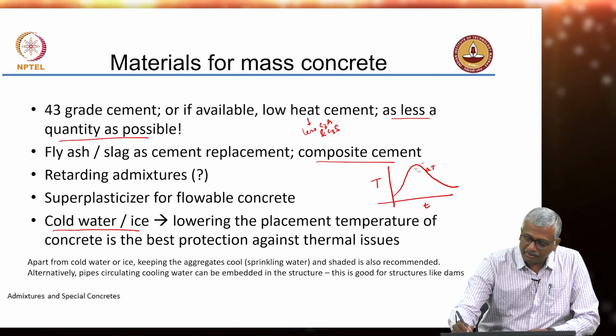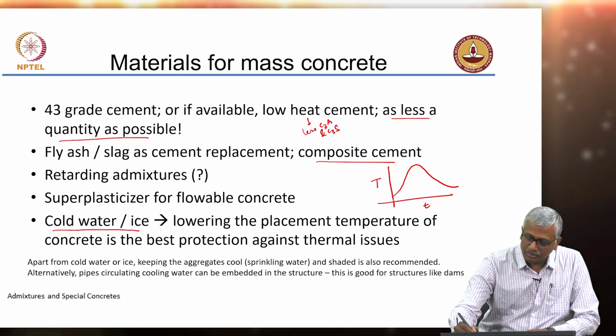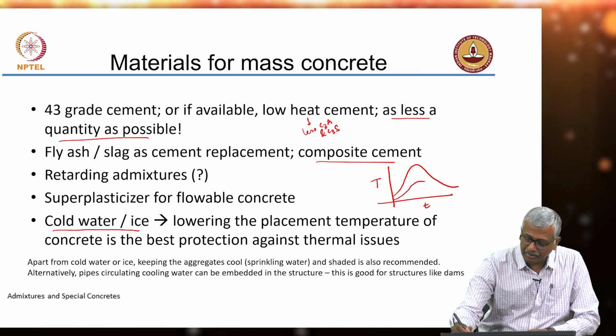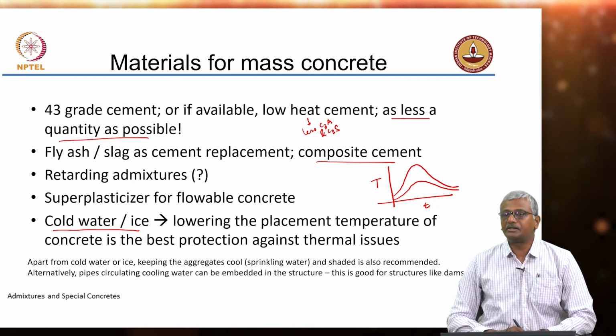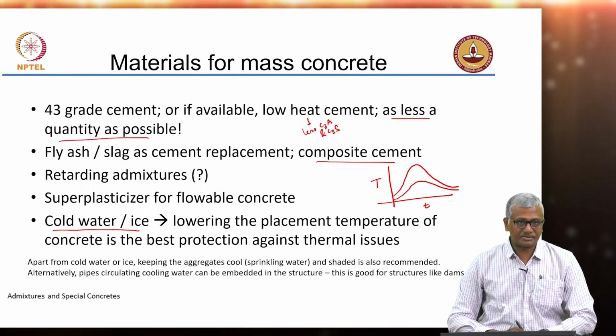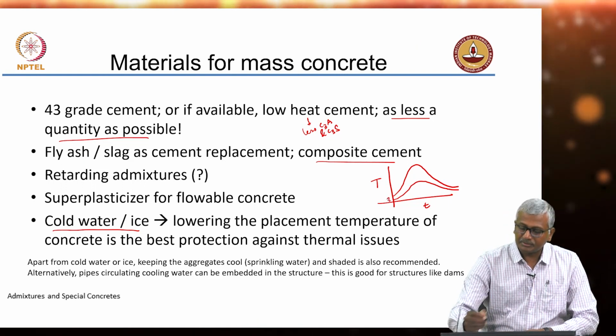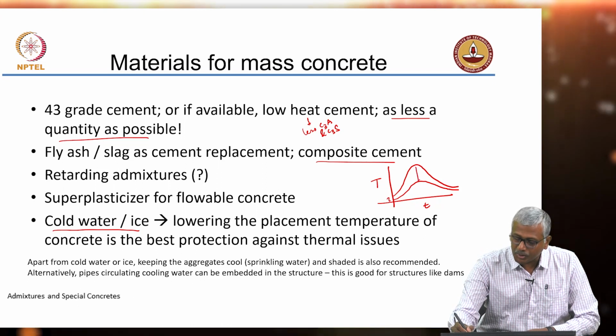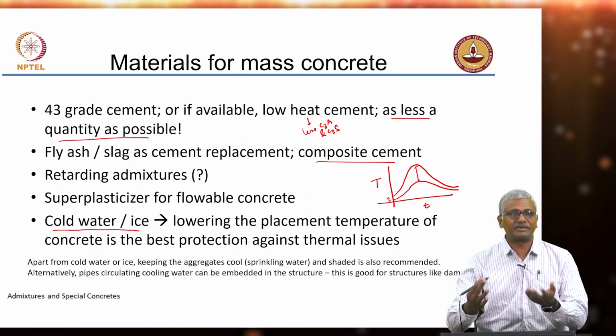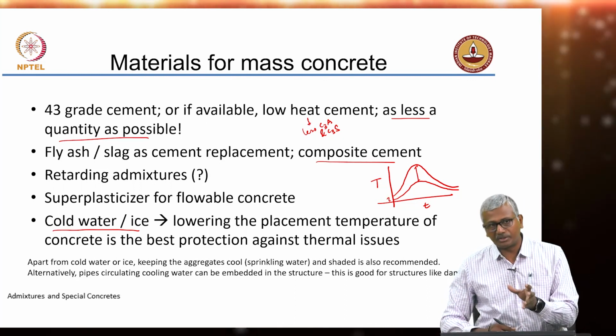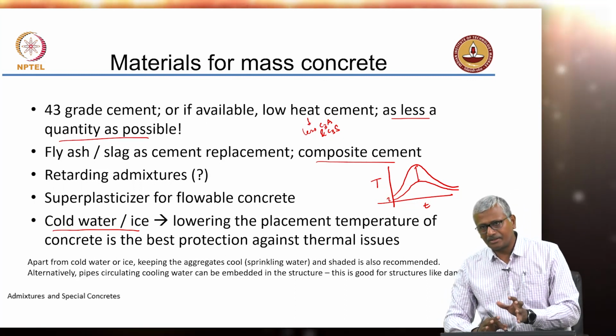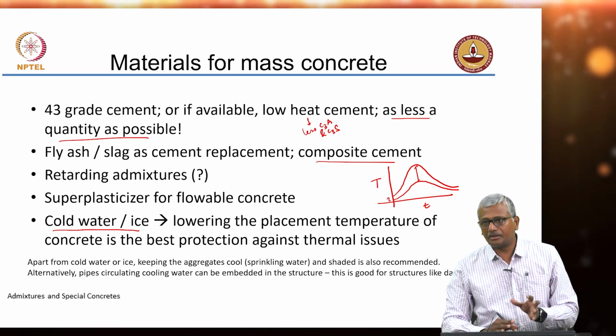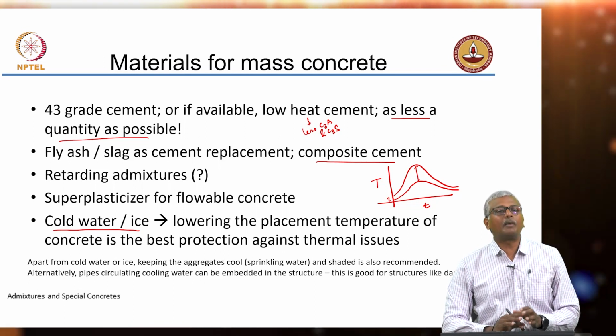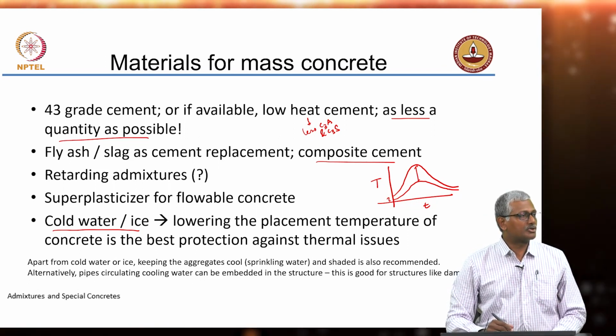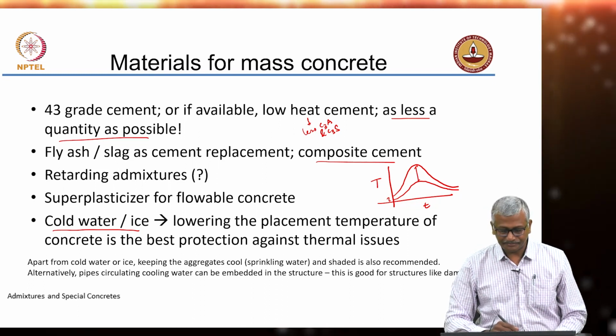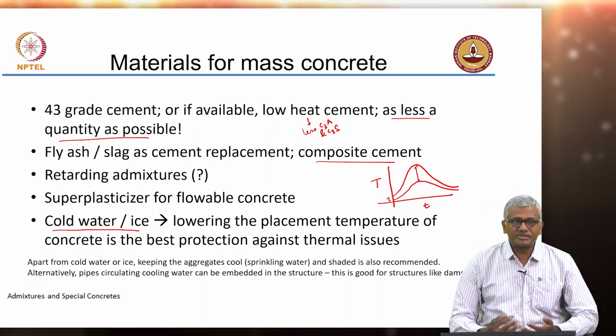So, what do you do when we use ice? What we are trying to do is lower the placement temperature itself, and that completely lowers the peak temperature that you get in the system. Okay. Now, lowering the placement temperature by x does not mean that the peak temperature also comes down by the same x. It can come down by more than that also, but more or less it is nearly the same. So, if you want to really reduce the heat in your concrete, the best and most optimal strategy is to simply reduce the temperature of placement to as low as possible. Okay. Now, it is not just enough, of course.